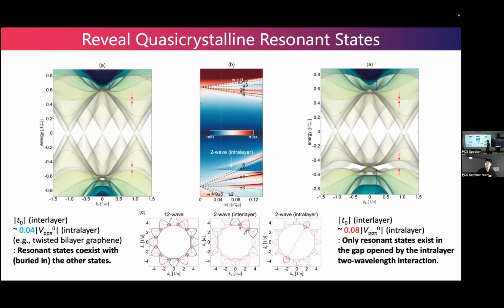And here I plot the density of states as a function of energy and interlayer interaction strength. The white dashed line shows the configuration of a graphene quasicrystal. The quasicrystalline state is not the only state at that energy. It coexists with the decoupled states and also many other two-wave mixing states. So it's quite difficult to observe the quasicrystalline states alone.